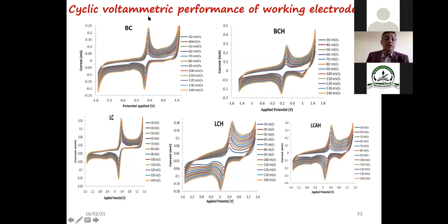So here the different materials we have used. This is the bentonite, okay, pristine bentonite. This is the local clay, pristine local clay. Now you see the different cyclic voltammograms that we will be getting. The interesting thing is that the peak current that you will be getting is going to increase when you are modifying the materials. If the peak was somewhere around 0.14, now it has reached more than 0.18, and in this case it has reached almost 0.4. That means the electroactive surface area is going to increase significantly, or the electrochemical signals are increased significantly.